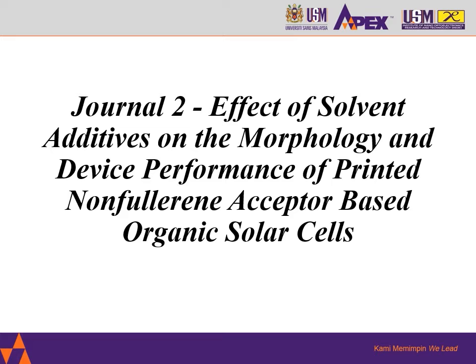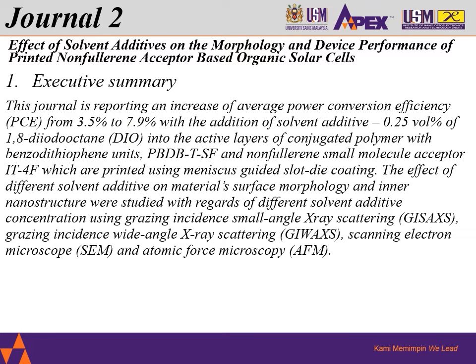Next, we'll go to the second journal, which is the effect of solvent additives on the morphology and device performance of printed non-fullerene acceptor-based organic solar cells. So in summary, this journal is reporting an increase of average power conversion efficiency, PCE, from 3.5% to 7.9% with addition of solvent additive, which is 0.25 volume percentage concentration of 1,8-DIO, into the active area of conjugated polymer with benzodithiophene units, PBDB-T-SF, which is the donor, and nonfullerene small molecule acceptor, which is IT-4F.